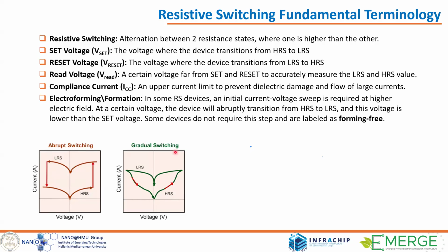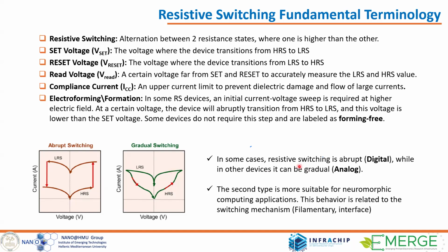There are also some types of memristors with a gradual switching. Here you see we don't have an abrupt transition, but a more gradual one. These two types are associated, at least for the perovskite community, with two different modes. The abrupt one is related to a filament formation. So actually we have a conductive path between the electrodes of the memristor. That's why we have this abrupt transition, while the gradual switching is associated with the accumulation of charges at the interface, not a filament formation. That's why the switching is not very abrupt.